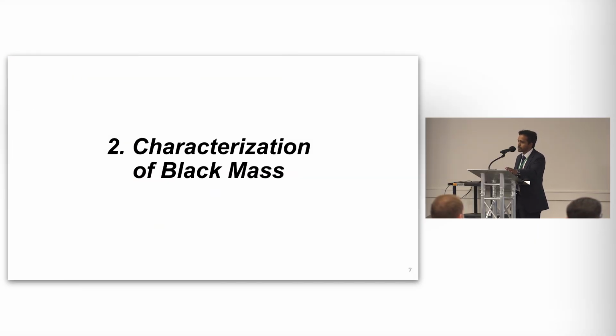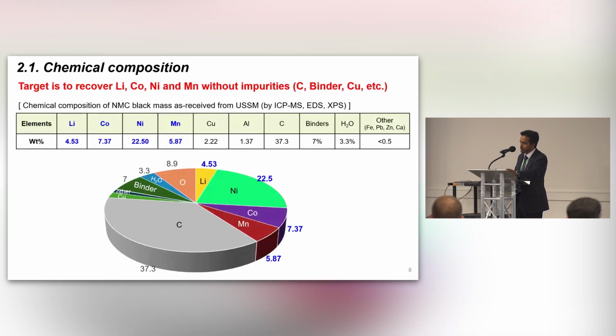So let's move into some highlights about our characterization. This sample we obtained from the US Strategic Metals Company. This is the NMC type black mass that contains high nickel, around 22%, and lithium and manganese around 5% each, and cobalt 7%. The challenging thing is that it contains a significant amount of graphite, around 40%, and binders around 7%.